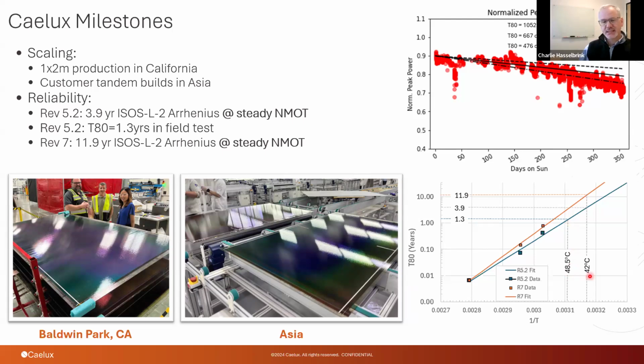And the reason is really clear. We were testing these at UC Merced with Sarah Kurtz, and those panels were running in a hotter environment, so it's not terribly surprising. But the other thing is that this is an Arrhenius plot, and it's got a pretty high activation energy. That means that those hot days where you're actually exceeding 48.5 and exceeding NMOT, where the wind's not blowing too fast, really matter. They'll really start shortening the life.